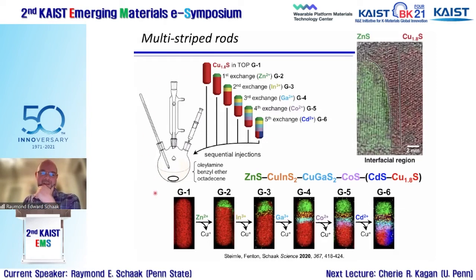And the setup, obviously this is a simplified version, but this is benchtop chemistry. This is fairly straightforward, a flask on a Schlenk line, basically just standard solvents that you would use for nanocrystal synthesis. And we start by injecting in the copper sulfide nanorods. Then let's take these five metals that I showed earlier, when I showed the crystal structure of copper sulfide and the five products that we make pretty often. Let's take those five cations, zinc 2 plus, indium 3 plus, gallium 3 plus, cobalt 2 plus, and cadmium 2 plus, and we can sequentially inject substoichiometric amounts of those.